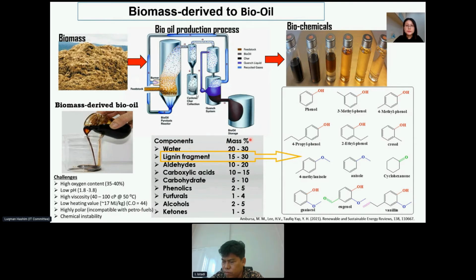So the major components of the bio-oil are water and lignin fragments, right? So these lignin fragments are actually phenolic compounds. Okay, they are present in ring-type structures, which can potentially fit into those petrol-based structures for chemicals and fuels applications. That's why here we come with the upgrading process, which removes these oxygen atoms in order to achieve a higher hydrogen-to-carbon ratio, which can help to improve the quality of the final products for biochemicals and also for biofuel production.